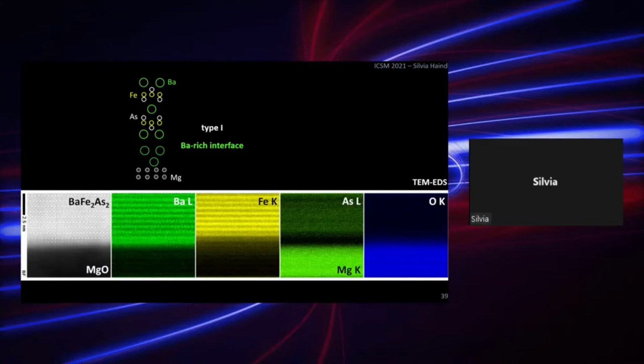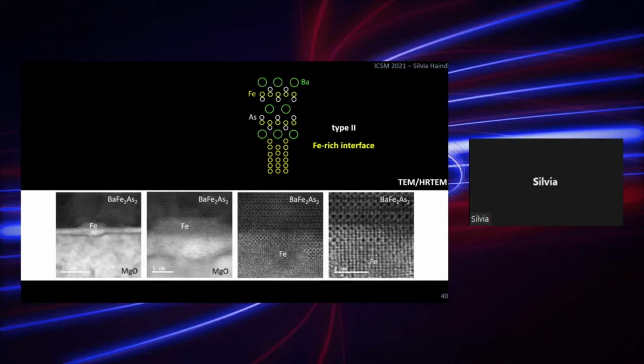One type of the interface is barium rich, and you can see clearly that we have additional barium layers between the BaFe2As2 unit cell and the MgO, which cannot be resolved unfortunately due to the strong contrast here, but you can see clearly additional layers of barium atoms. In addition, the TEM-EDS mapping shows also a large fraction of barium at the interface, so a very strong barium signal there, and a lack of arsenic and a decrease in the iron. On the other hand, we also find an iron-rich interface, so we can find sometimes at the interface that iron islands are formed, and these iron islands then form the, as already known, 122 iron interface, which is also a clean one then.